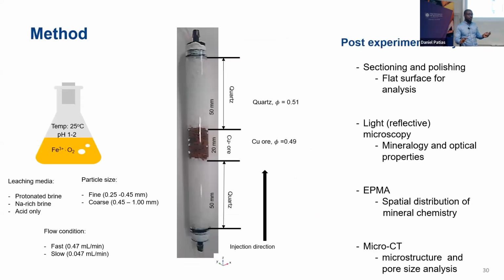So we use very tiny columns because we wanted to micro-CT them before and after. The micro-CT machine is small, we can't put a very large column in it. So we used a very small column size, packed some quartz from Bunnings at the bottom and at the top, and then put your copper material there. This was pure quartz. We tested this with XRD mineralogy and yeah, it was pure quartz.